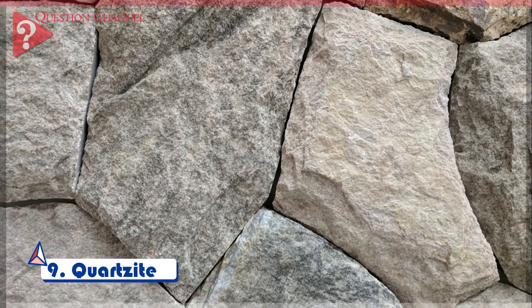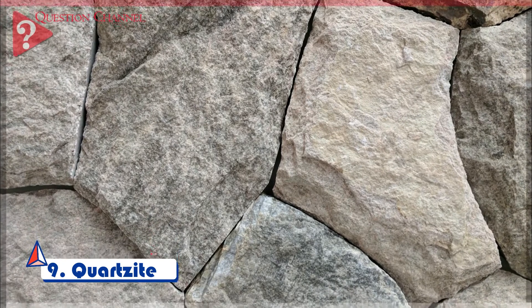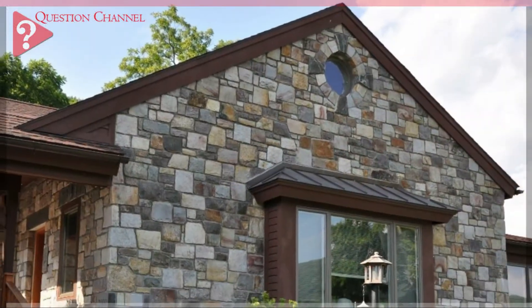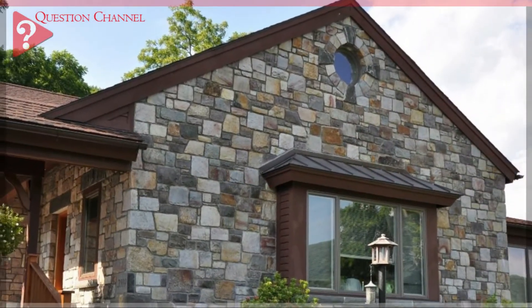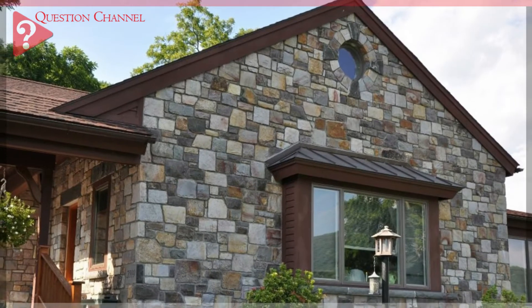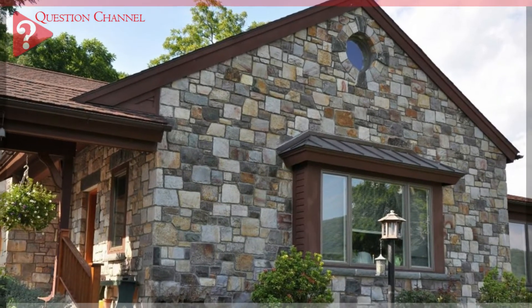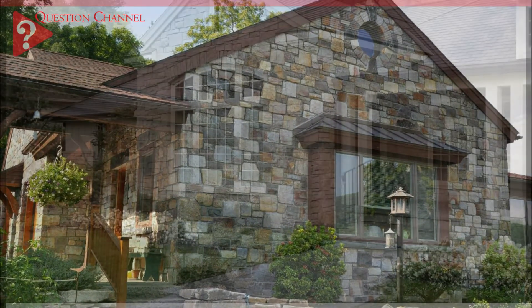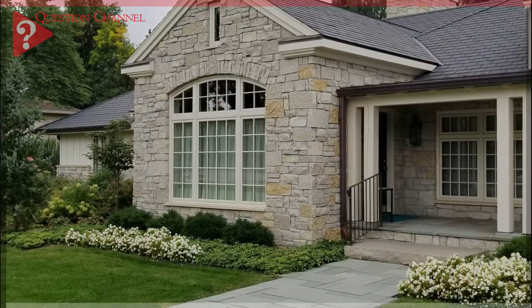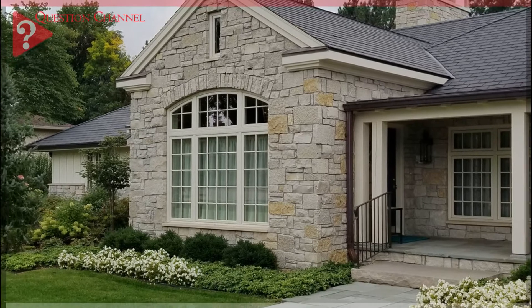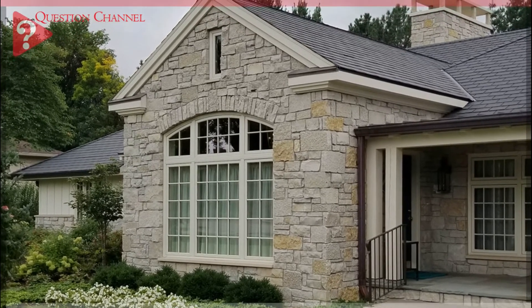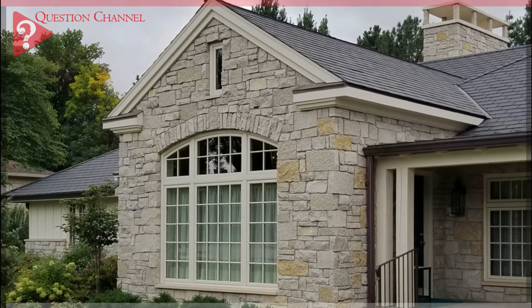Quartzite. It is used as building blocks, slabs, and as aggregate for concrete. The structure of quartzite is fine to coarse grain and mostly granular and banded, mainly composed of quartz, with feldspar and mica in small quantities. The crushing strength is between 50 MPa and 300 MPa. They are available in different colours like white, grey, and yellowish.